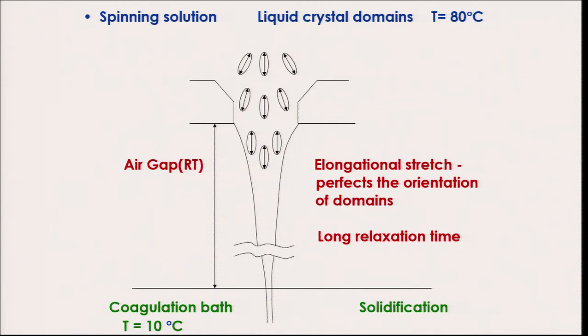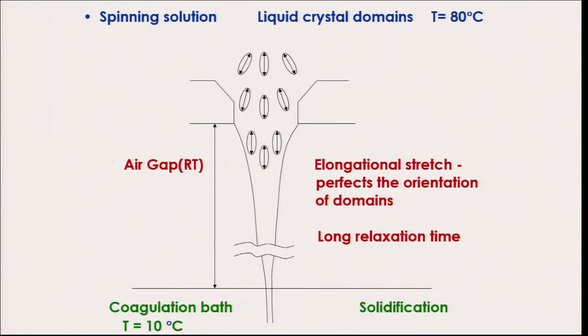which is in contradiction to melt spinning, where the polymer will show die swell, right. And not only that, these polymers have very long relaxation time. Long relaxation time means they relax very slowly. So, therefore, before they relax, they are solidified, they are converted to the solid fiber in the highly oriented structure itself. This means that the highly oriented domain structure which was present in the polymer solution is also converted to the solid fiber because of the elongational stretch and the long relaxation time.